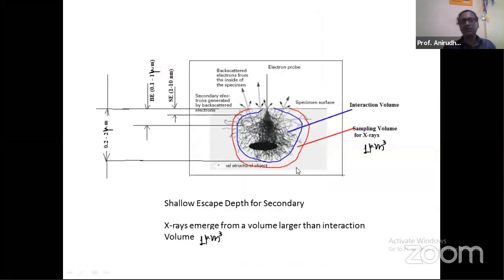The reason being this: when a narrow beam enters into this matrix, X-rays would emanate from a very large volume, because those electrons which manage to enter would penetrate into very large volumes, and then X-ray emission would happen even from a volume which is slightly larger than that. This is called the sampling volume, which is slightly more than the interaction volume between the electrons and the particles of your matrix. And this sampling volume is roughly about 1 micrometer cubed.